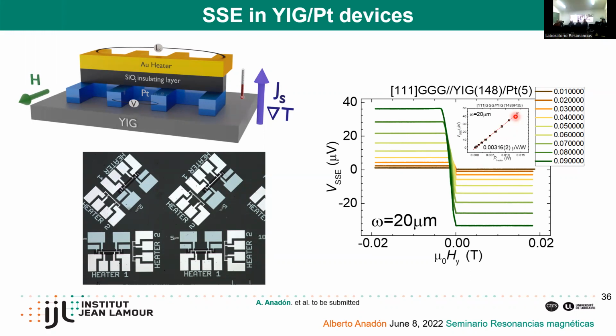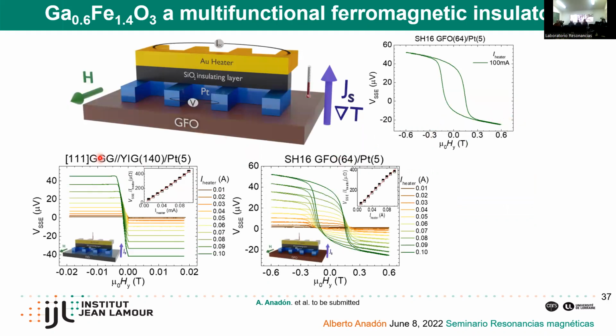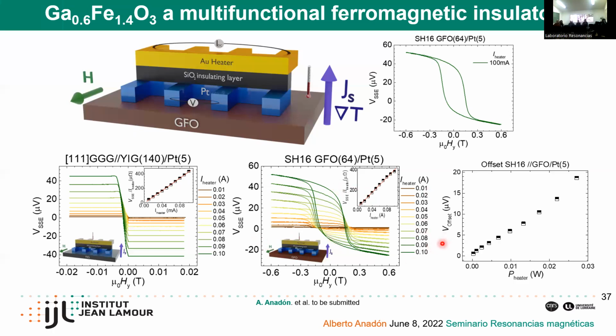And we can go and measure also this in GFO. So YIG, as you know, YIG is the yttrium iron garnet, is the cornerstone of spintronic ferromagnetic materials in terms of insulating materials, because it's one of the most used generally. So we can see just by comparison that we have similar voltages in both yttrium iron garnet and GFO devices, similar to the ones that I'm just showing. In addition, if you look carefully, you could see that the hysteresis loop is shifted when we are increasing the heater power, and this also scales mostly linearly with the heater power.